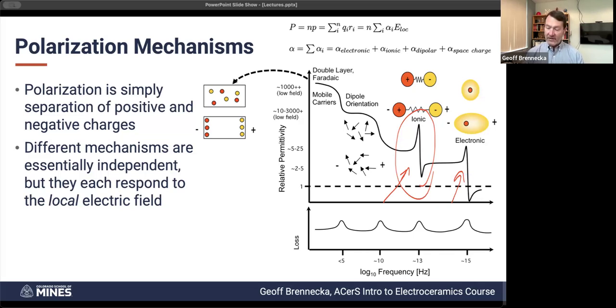You'll notice again, because of that resonance, there's a loss peak that happens right at that resonance. So it may look attractive that if you want to increase permittivity, you want to be right at one of these resonance peaks, but keep in mind that there's a broad distribution of these, and if you're at the very peak of one of them, then you're going to be at the minimum part for another one, and this in-between part is where the loss is maximum. And so if you want to dissipate energy, hanging out at one of these resonances is great. If you want to actually store it, it's a dangerous balance to try to match.